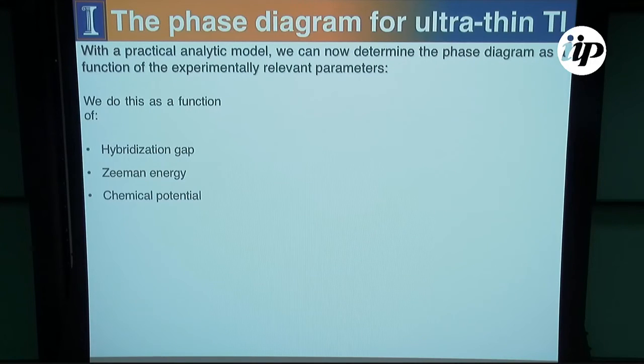Now that we have this simple picture, we can calculate a phase diagram. We can do this by looking at the band closing points within the topological insulator as a function of the magnetization, as a function of the chemical potential, and as a function of the hybridization gap.